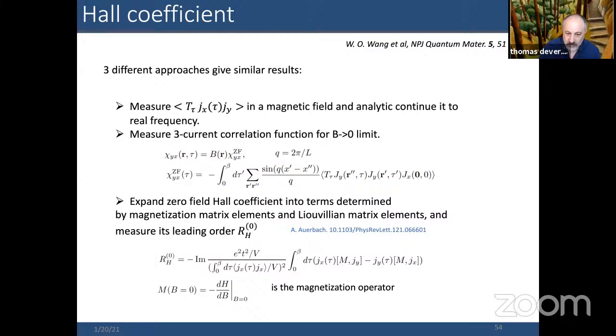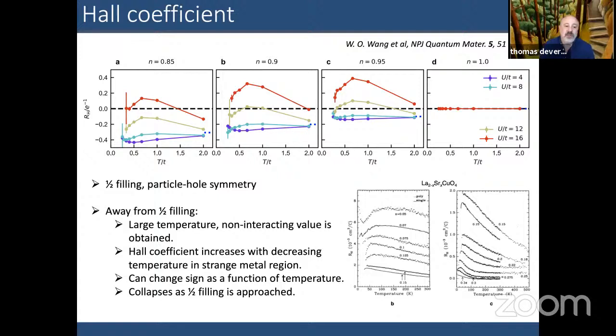So I'm just going to show you one set of results, which is the Hall coefficient plotted from quantum Monte Carlo for four different fillings, starting at half filling. There's no T prime in this, so we have particle-hole symmetry at half filling. So the Hall coefficient is dead zero for U of 4, 8, 12, and 16 for all temperatures. And then as one dopes, the Hall coefficient becomes temperature dependent and depends on U. If U is small, the Hall coefficient is less temperature dependent, but as U gets larger, on the order of 12 or 16 T, the Hall coefficient increases as temperature decreases and can change sign.